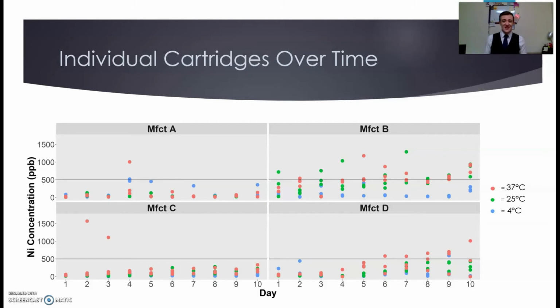We also begin to see a temperature dependence, with many more of the red and green dots, being the 37 and 25 degrees Celsius environment, being above that action limit than the blue 4 degrees Celsius dots, indicating that there could be a temperature dependence. More on this relationship later.